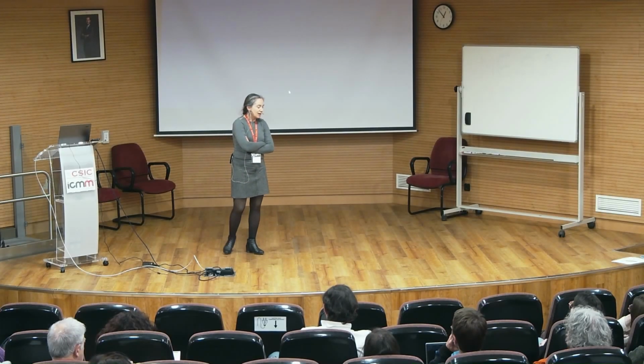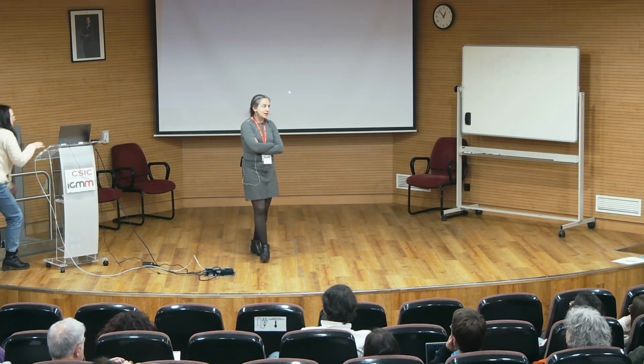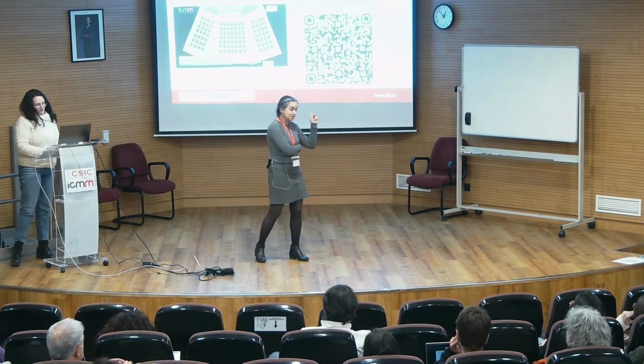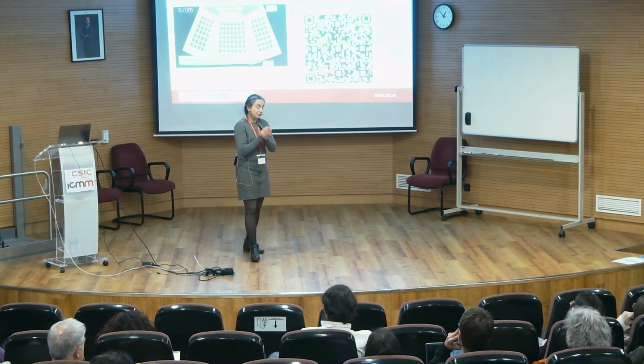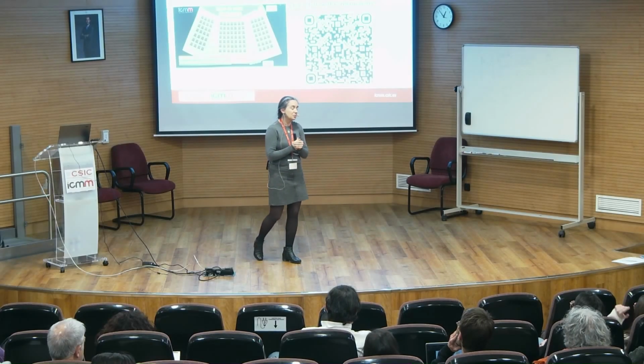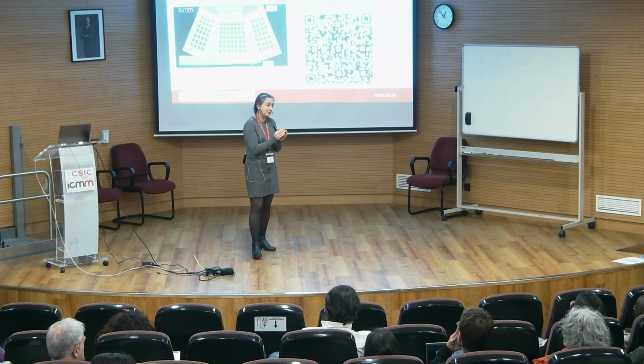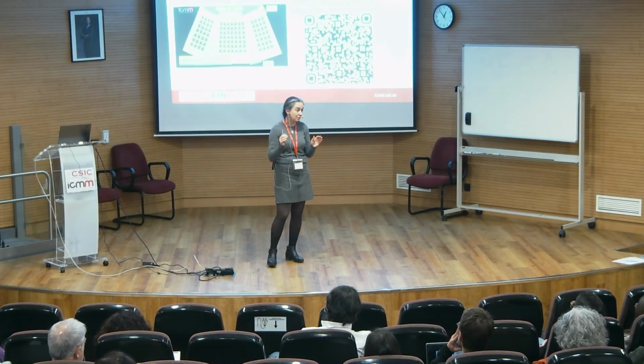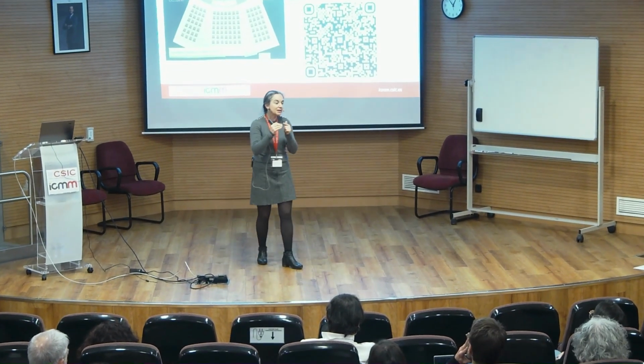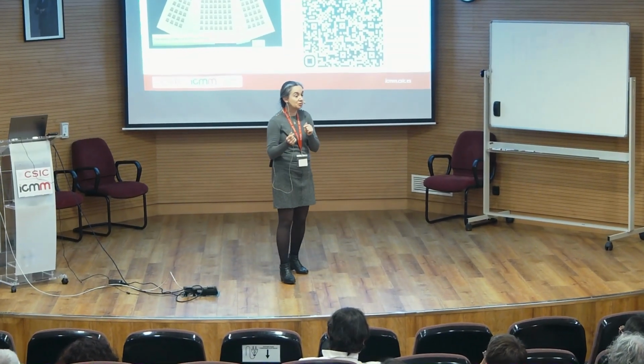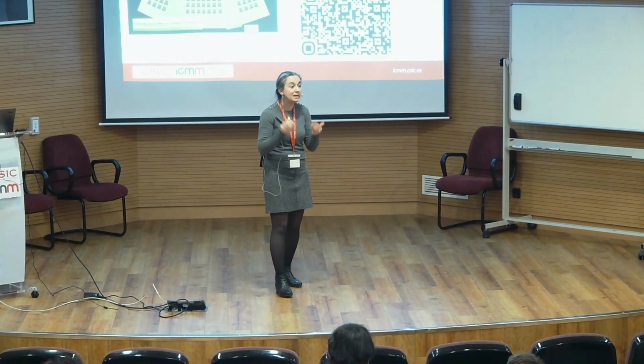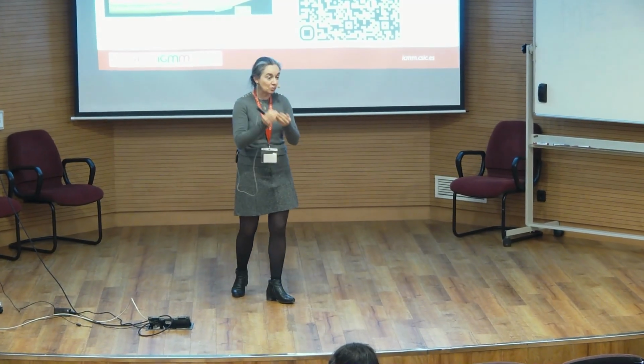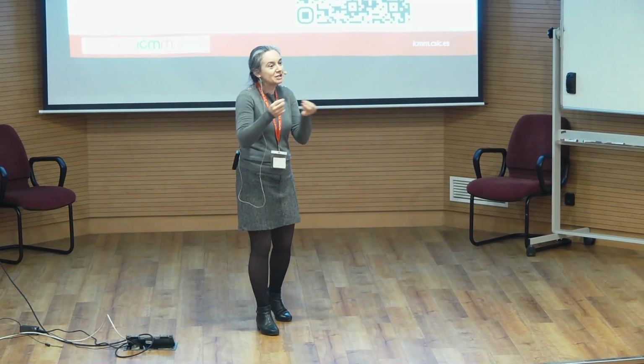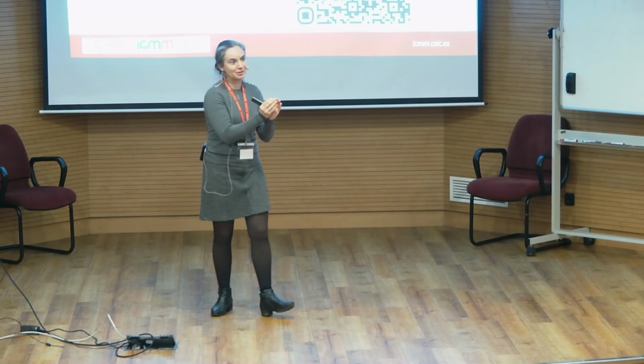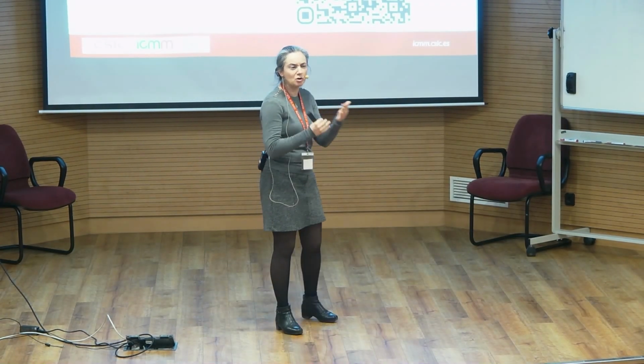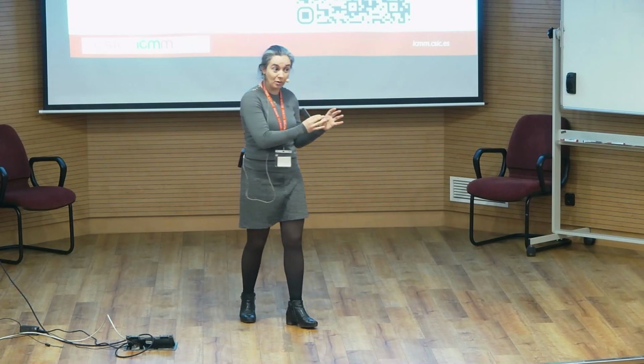Regarding your question about the degradation, yes, we did. In those 4 months of implantation, we studied how the scaffold was. First, we measured by using atomic force microscopy, in collaboration with Ricardo, the mechanical properties of the scaffold after 4 months of implantation. What we found is that the mechanical properties were a little bit increased, and not because of the reduced graphene oxide, but because of the infiltration. It was completely populated by proteins that were deposited and cells, and we couldn't separate them while maintaining the structure of the 3D component. So the mechanical properties don't go much farther than where they were, which is good.